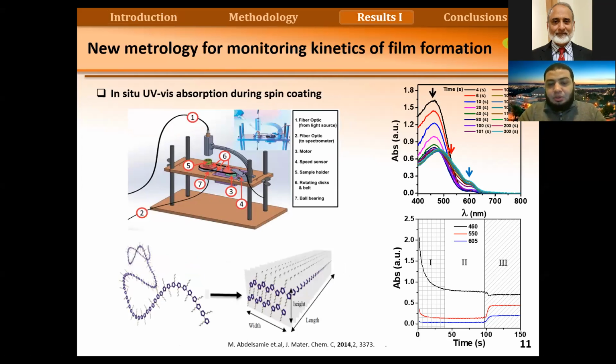And so what I'm trying to do is in situ characterization in order to understand this process. The first topic that I worked on during my research is to make a new technique that can probe the film formation in situ. I have made a new device that can help us do in situ UV absorption during spin coating. If someone doesn't know what spin coating is, we start with a solution. As you can see in this picture, we add the solution onto our substrate, and then a motor spins this substrate at high speed to form a final film.